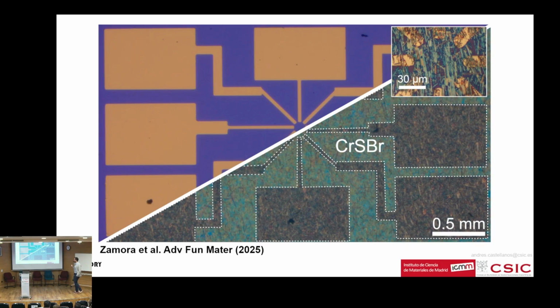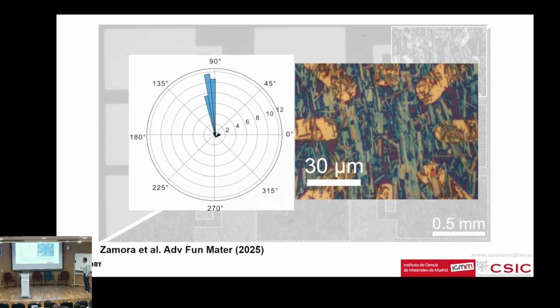So you can even fabricate electronic devices exploiting this kind of inherent anisotropy, right? We have this chromium sulfur bromide material. We have these electrodes at different crystal orientations, fabricated to test different crystal orientations. When we transfer the crystals, you basically get all these elongated crystals here. There is, of course, some degree of disorder, but overall, if you do a polar histogram, you see that most of the crystals are oriented along the same direction.